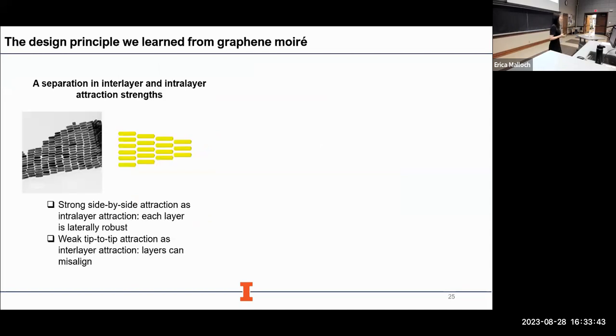So that's what we realized if we use gold nano rods showing here, which is the most anisotropic gold nanoparticle building block. So with the gold nano rod, you can have very strong side-by-side attraction, which can be used as the intralayer attraction to make sure you have a very coherent layer, which is analogous to the covalent bond in graphene moire. But at the same time, you can have very weak tip-to-tip attraction as the interlayer attraction, so the layers can misalign with each other, which is analogous to the pi-pi or van der Waals attraction of graphene moire.